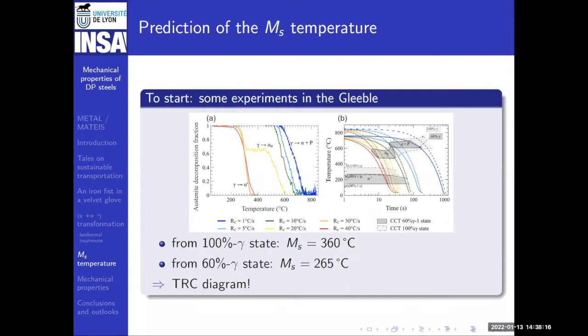Okay, so now we have a model to predict what is the fraction of austenite which transforms into ferrite or, on quench, into martensite. But it would be nice if we had another model to predict what we call the MS temperature, which is the temperature at which, during the quench, austenite transforms into martensite. Okay? So there have been many studies to guess, depending on the steel composition, the martensitic start of the steel.